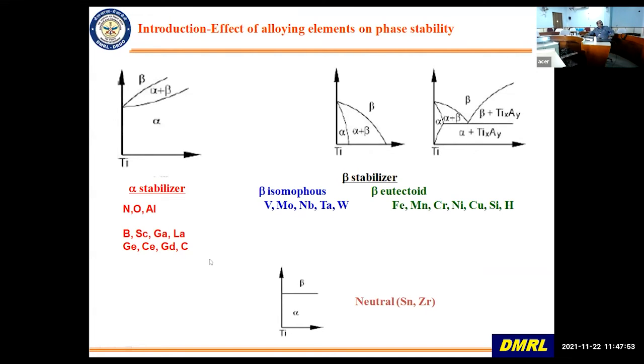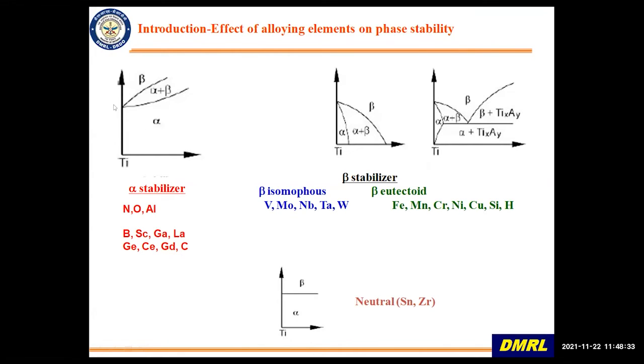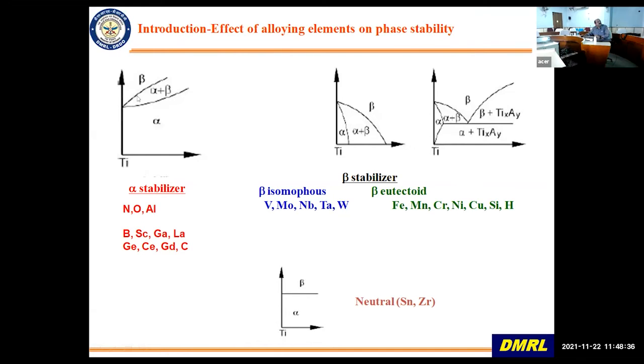titanium alloys, here I'm just showing you how the classification is done. The alloying elements are basically divided into two categories: the alpha stabilizers and the beta stabilizers. Now, what do alpha stabilizers look like? These are the elements, and one of the main important ones is aluminium, along with oxygen and nitrogen, and the rest are less used. If you see this part of the phase diagram, when you add an alpha stabilizer, it stabilizes the alpha phase field and increases this temperature line, which is called the beta transus temperature line.